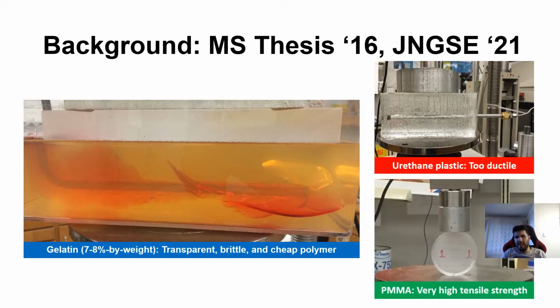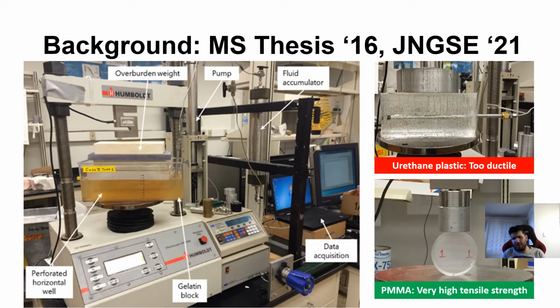Another material was PMMA, which is basically bulletproof glass, and this was brittle, unlike urethane, but has very high tensile strength of about 10,000 psi. And this makes it very hard to break with the equipment and apparatus that you find in a typical geomechanics lab. This was the laboratory setup I used.